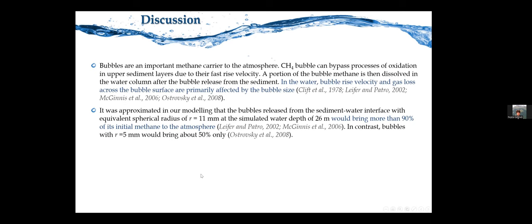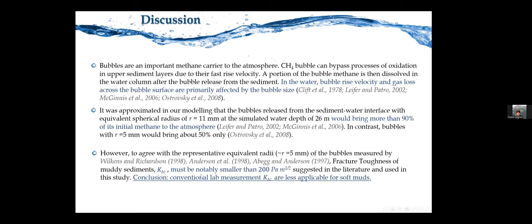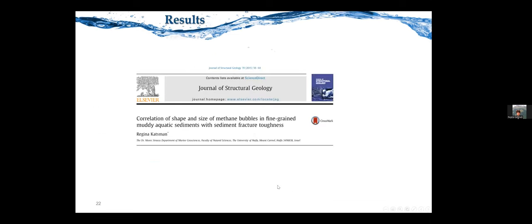And the simulation was performed with the fracture toughness of 200 suggested in the literature. So it is seen that there is some discrepancy, and it is known that muds are very soft material, and it can be suggested that conventional lab measurements of fracture toughness are less applicable for soft muds. So this is the conclusion. The following study was performed.